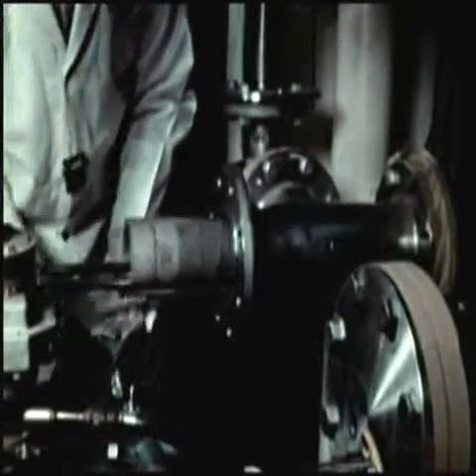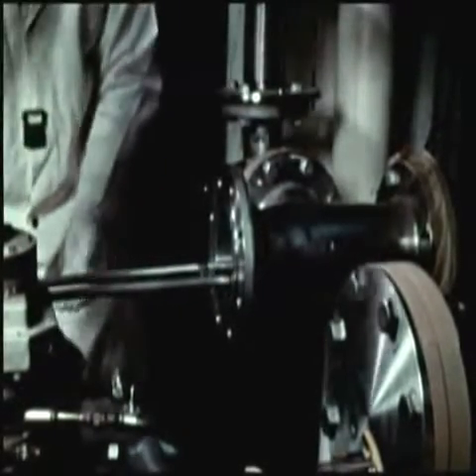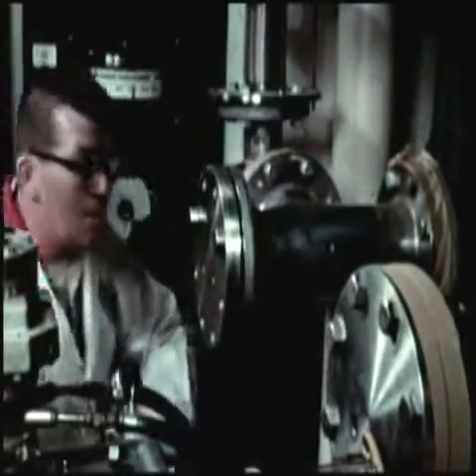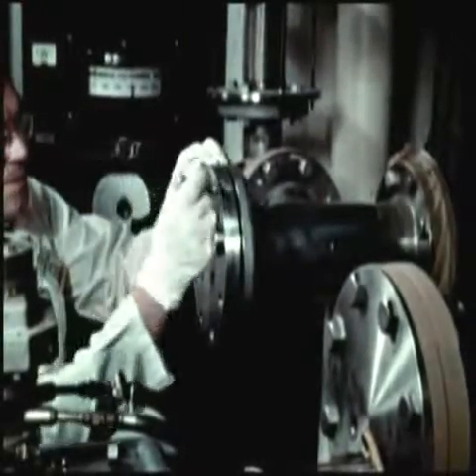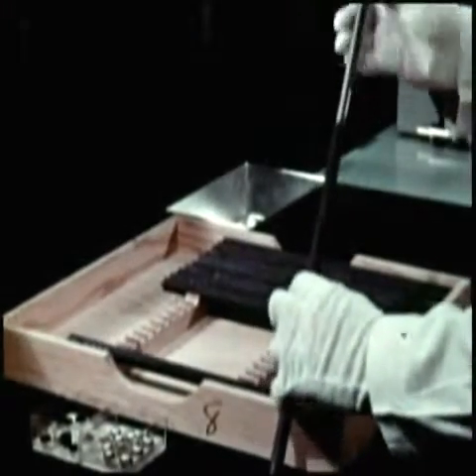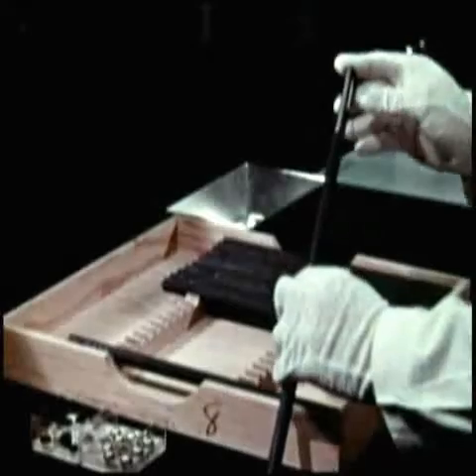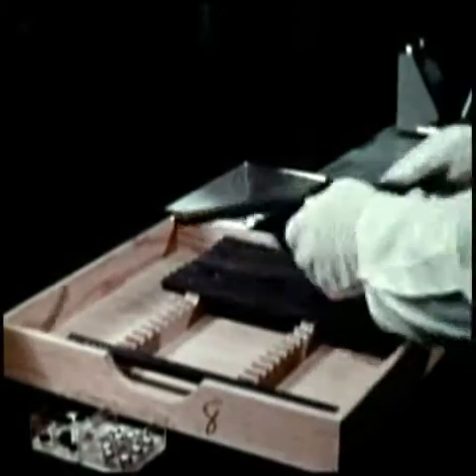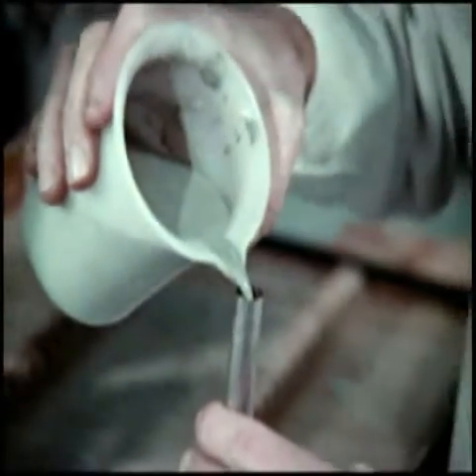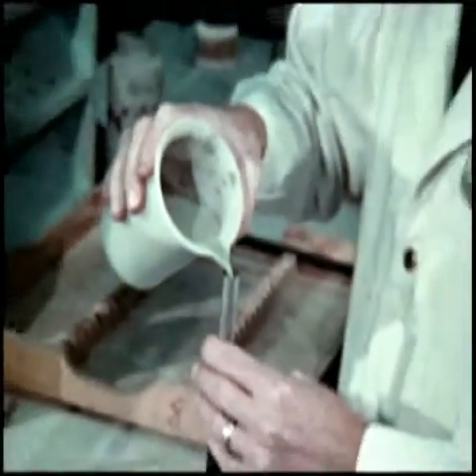The resulting hydrogen content of the material, when at 1,300 degrees Fahrenheit, is approximately that of ordinary water at room temperature. The hydrided rods are clad with chromized Hastelloy N tubes. To minimize hydrogen loss from the fuel at reactor operating temperatures, the internal surface of the cladding tube is coated with a thin ceramic coating.